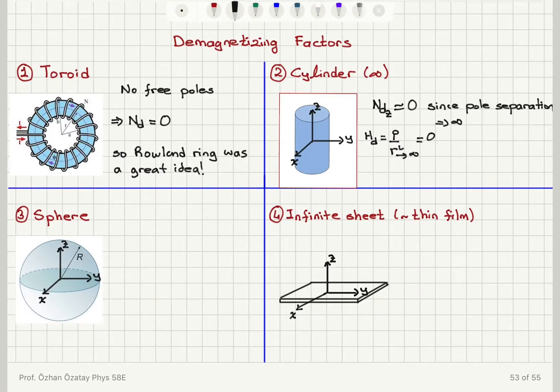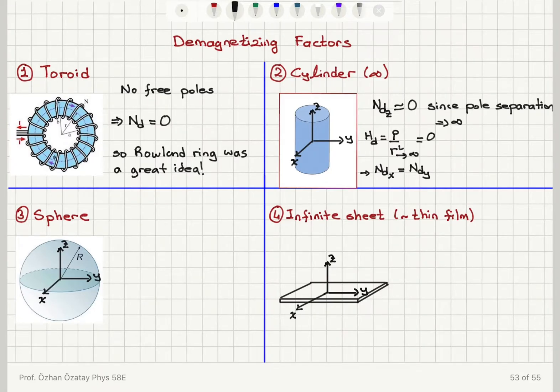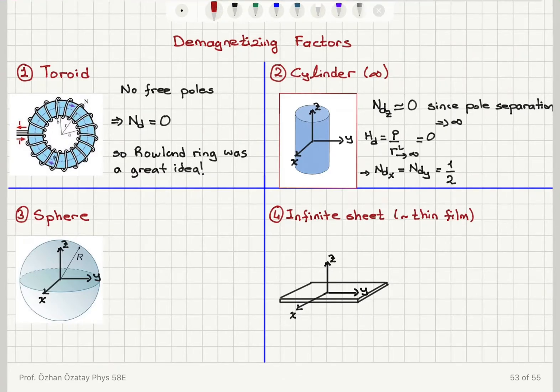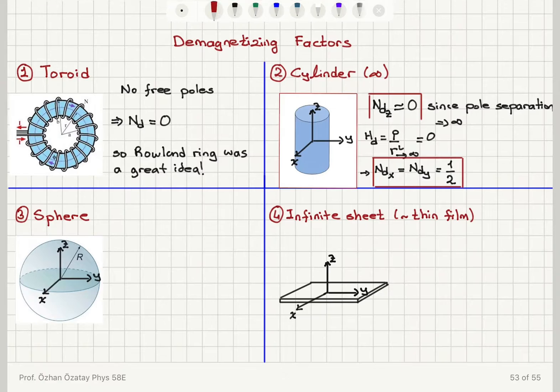So the demagnetizing field goes to zero in the z-direction. On the other hand, for the x and y axes, which are basically symmetric, the demagnetizing factor for magnetization along the x-axis equals the demagnetizing factor for magnetization along the y-axis because there is no preference. They have exactly the same shape, just a radial distance r from the center. So these demagnetizing factors are equal to 1/2. In the case of a long cylinder, we have approximately 1/2 demagnetizing factors along the radial axis and no demagnetizing factor along the length of the specimen.